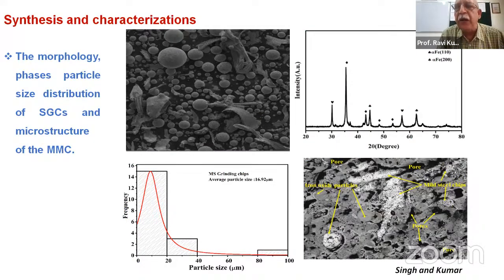If you look at the morphology of these particles, they have a very spherical morphology. And if you look at the structural phases, they have iron oxide in hematite and magnetite form, and alpha Fe, as X-ray diffraction studies show. Then we can see their surface morphology, and after sintering, we can find the morphology of these particles, which has iron oxide particles. There are some pores, and mild steel chips are present after sintering of these materials.